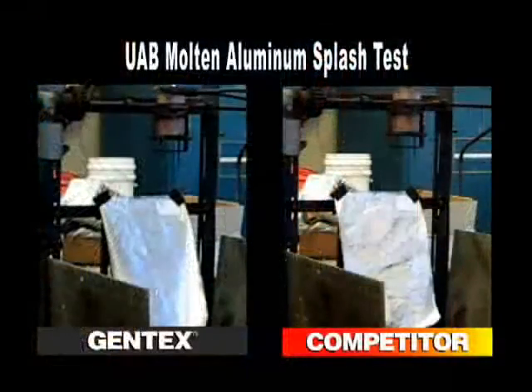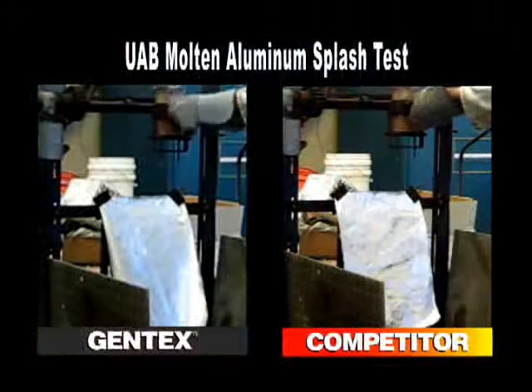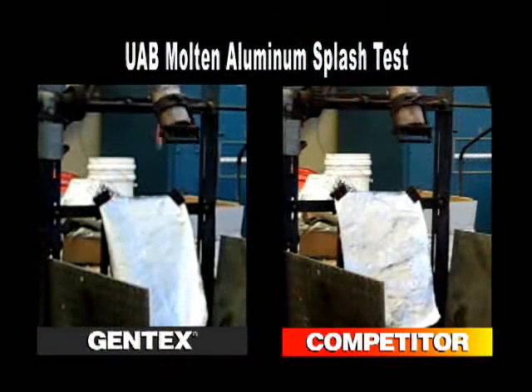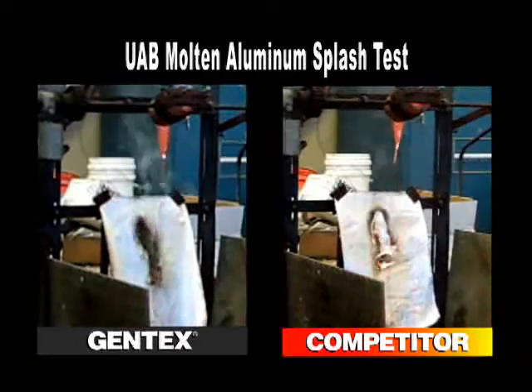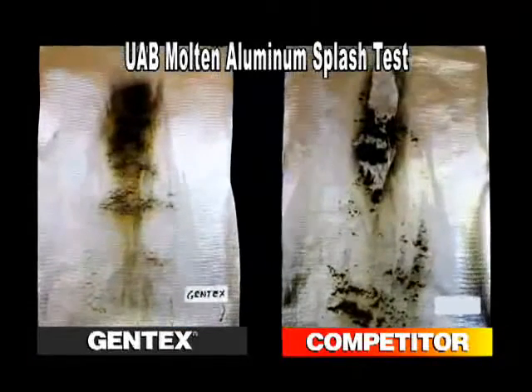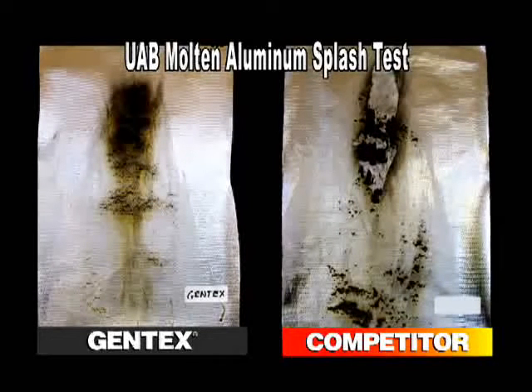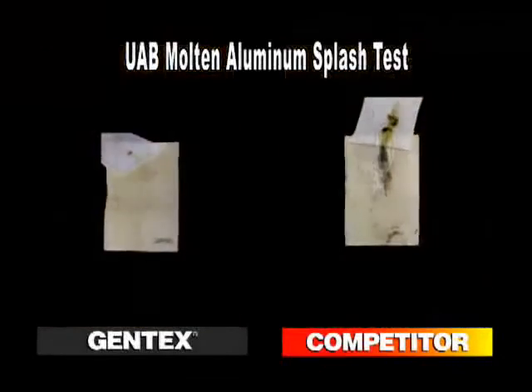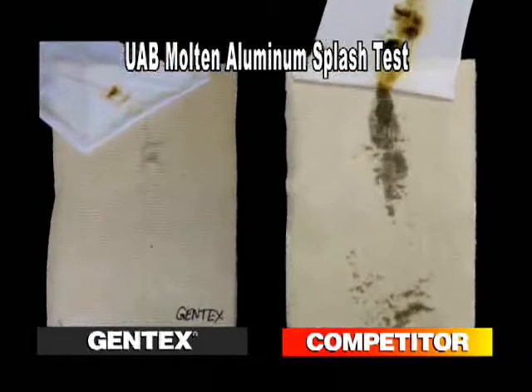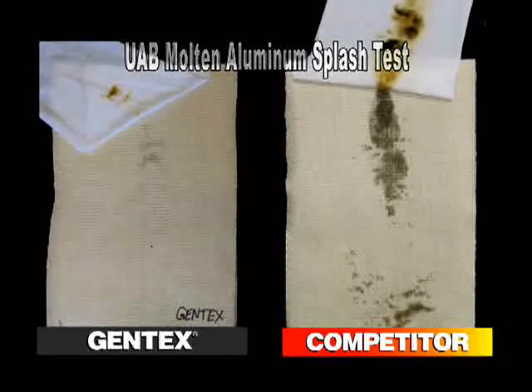Temperature rise on the back of the fabric is measured to determine heat transfer and the protective capacity of the aluminized fabric. In this side-by-side comparison, molten aluminum is splashed on a sample of the Gentex fabric on the left and the competitor's fabric on the right. Note that the competitor's fabric did not shed the molten aluminum, which results in an extremely high transfer of heat through the fabric, endangering the wearer. Based on this result, it would be less safe to wear a garment made of this fabric for use in protecting a worker against the splash of molten aluminum. On the other hand, the Gentex sample sheds the molten aluminum as required for maximum protection of the wearer.